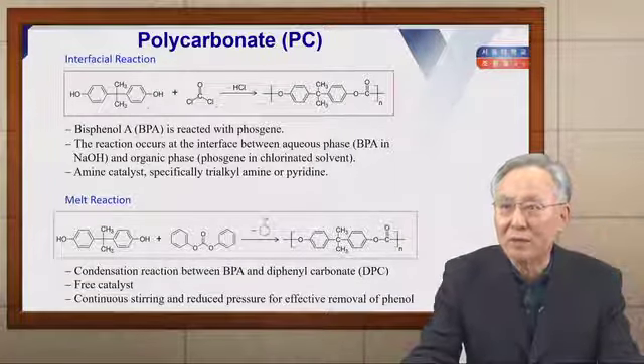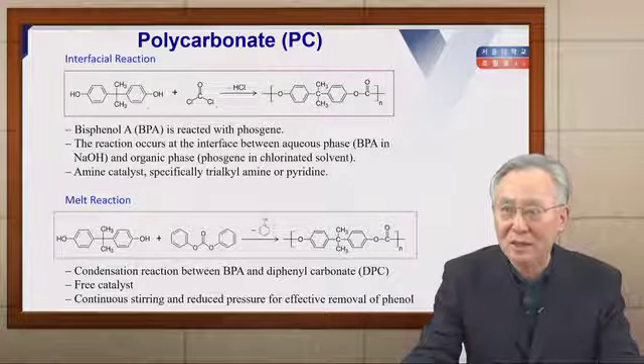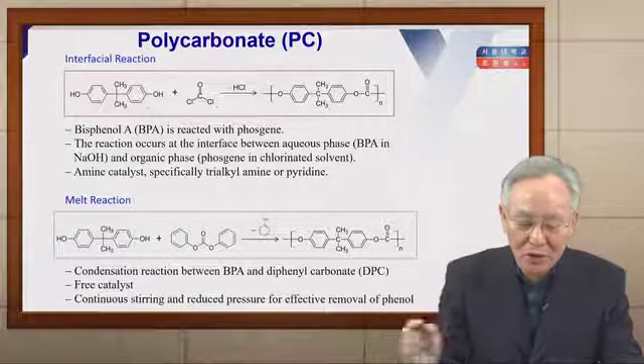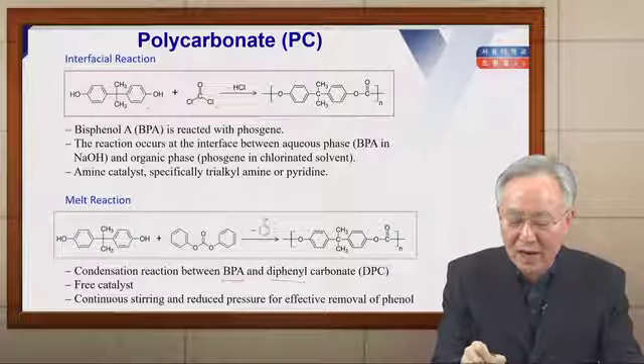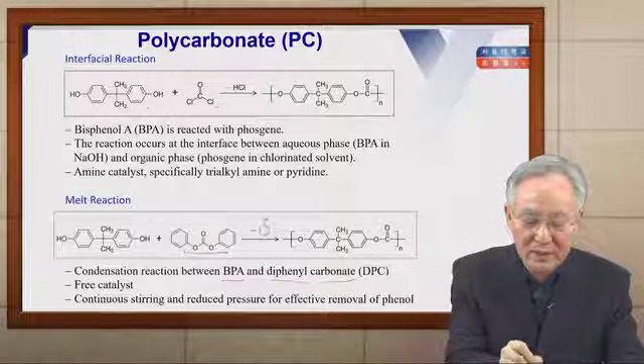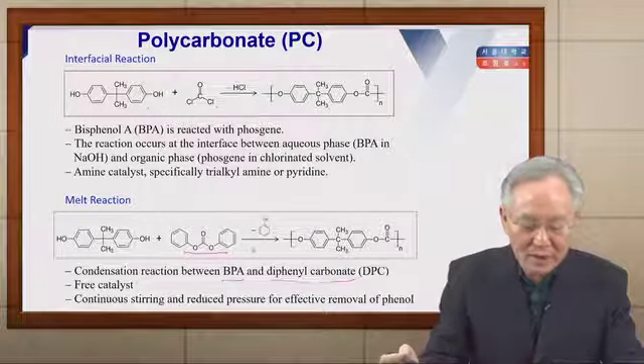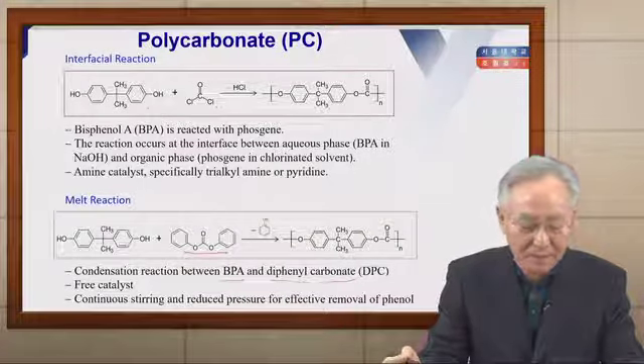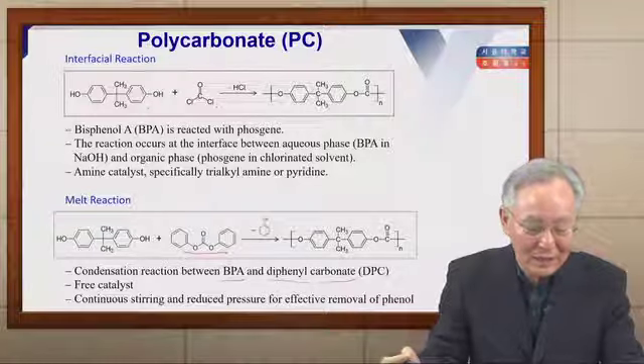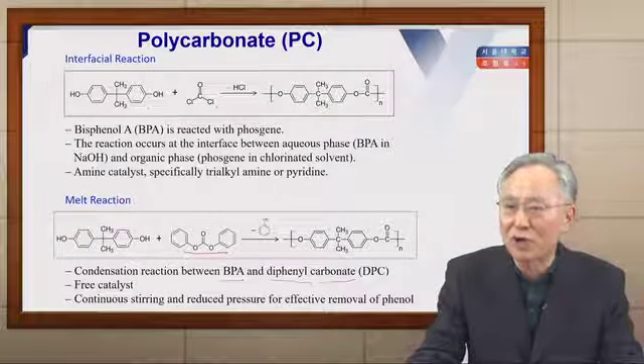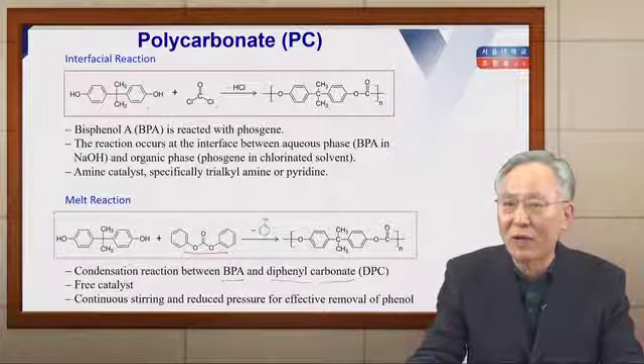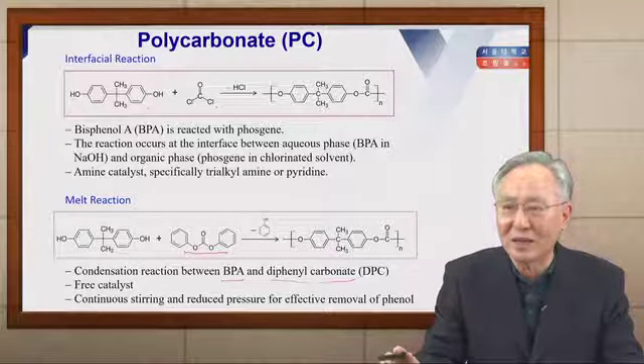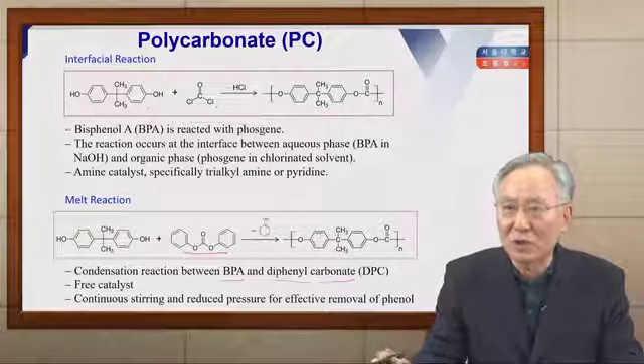The melt reaction is a condensation reaction between bisphenol A and diphenyl carbonate, with removal of phenol. In melt reactions, catalysts are not necessary; just continuous stirring and reduced pressure for effective removal of phenol are required. The melt reaction is commercially available, and most industries use melt reactions.